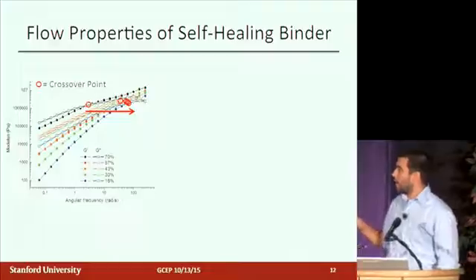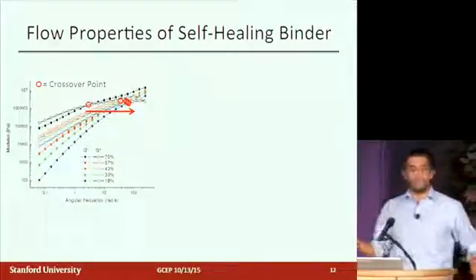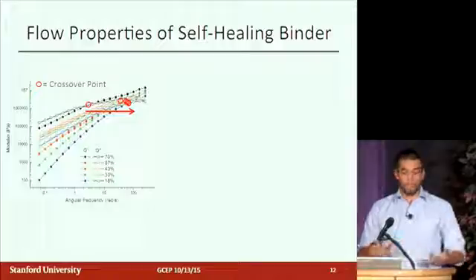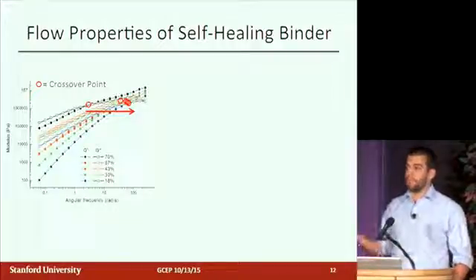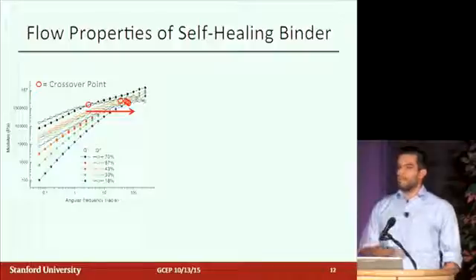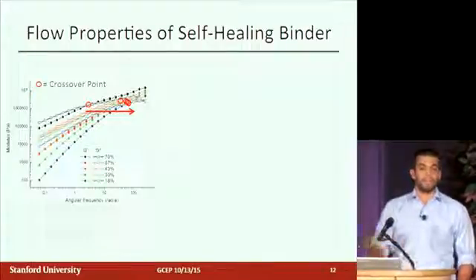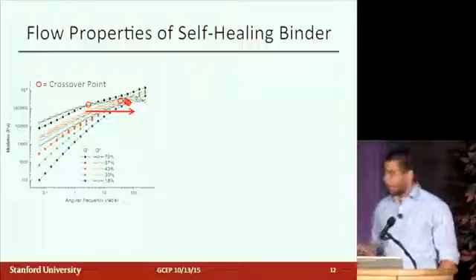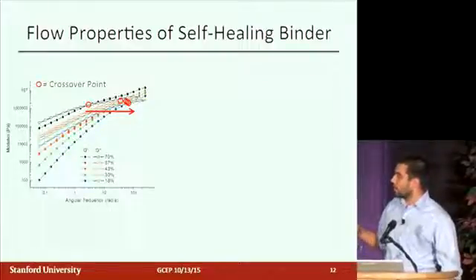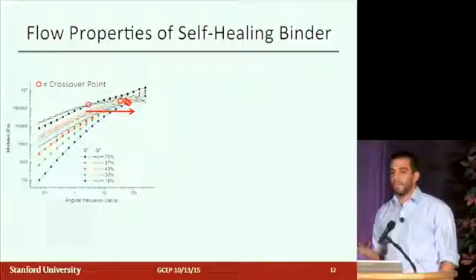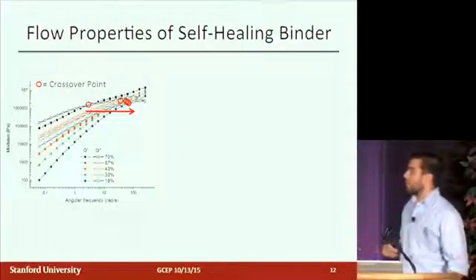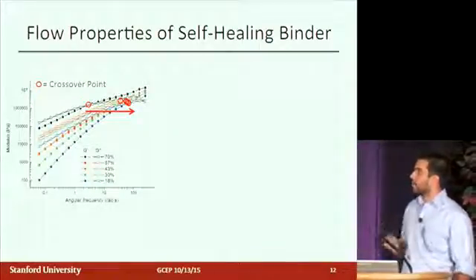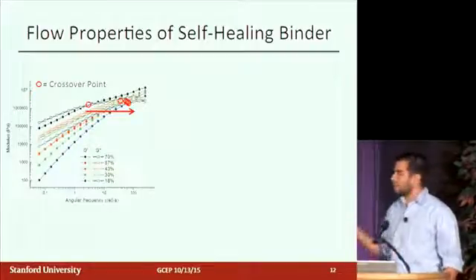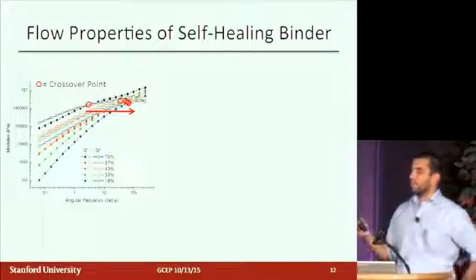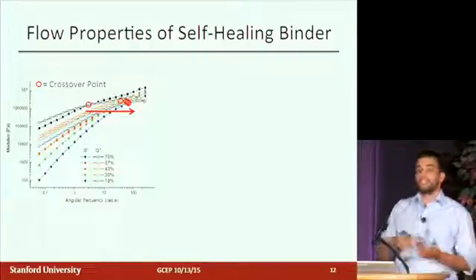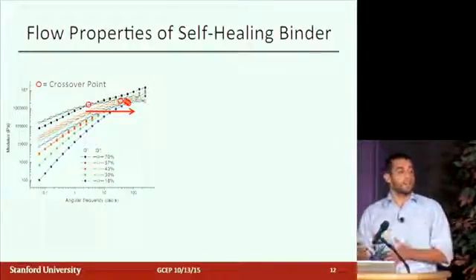Here, we're looking at a frequency sweep on a rheometer. You just take 2 parallel plates and you oscillate them at a low strain, and you change that frequency. At slow times, at low frequencies, you're probing more of a liquid characteristic of the material, and at fast times, you're probing it more like an elastic solid. The closed circles are the storage modulus, which is really the solid-like properties of the material, and the open circles are the loss modulus, which is more like the liquid part of the material. And where they cross over, that's what I've highlighted. That's where you can say that the material is transitioning from a liquid-like characteristic to a solid-like characteristic.